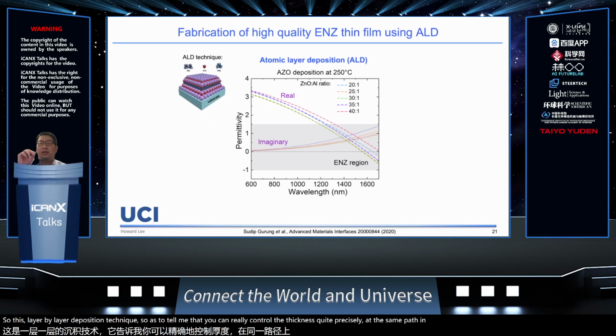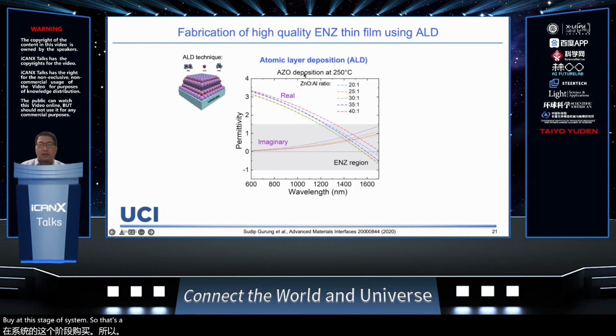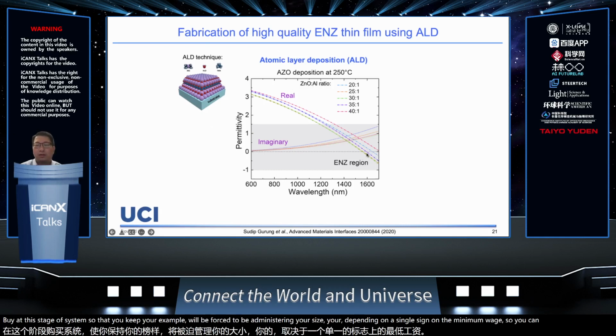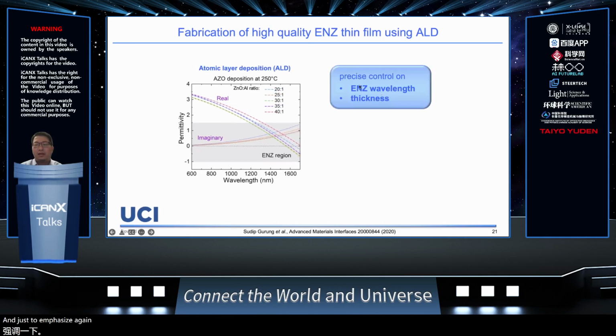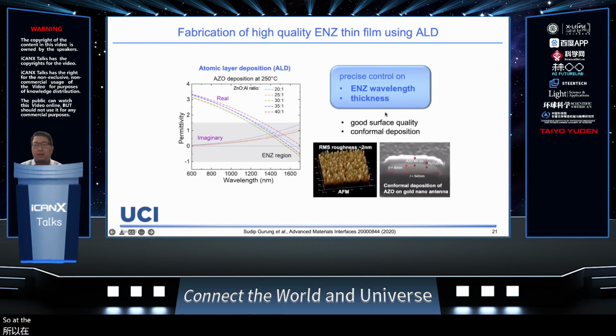At the same time, in each layer, you can control the conditions so that you can have different materials with this ALD deposition. Just to give you an example, we deposit aluminum zinc oxide, AZO. Depending on the zinc oxide and aluminum ratio, you can really tune this ENZ wavelength to different regions in the telecommunication wavelength. Just to emphasize again, ALD allows you to precisely control the ENZ wavelength and thickness, which is quite important for this ENZ optics study. It can also provide quite good surface quality, and you can coat conformally. That means if you have a metal surface, you can even coat the side wall of this metal surface quite easily. That's why we have been using this technique quite a lot to make this kind of ENZ material.